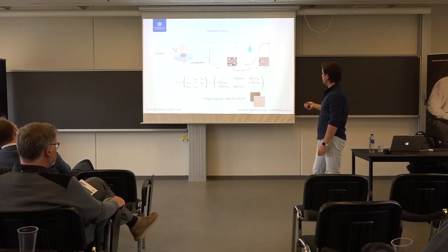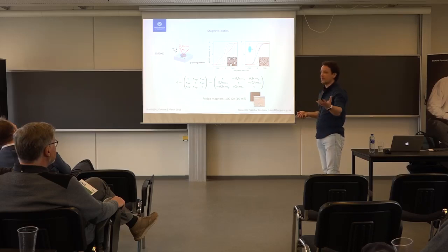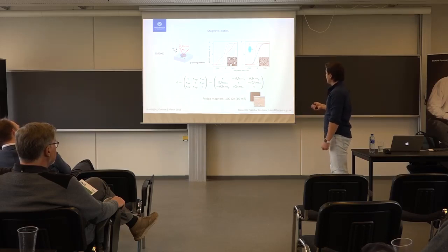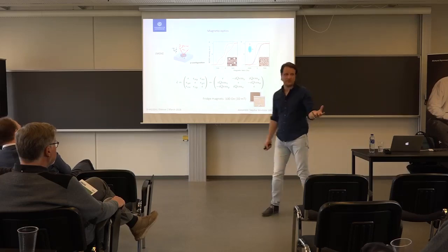Or here you would see the effect of applying the magnetic field along different axes. I mentioned the easy axis, where the material likes to be magnetized. It turns out that if you have an anisotropic structure like the ellipse, and you apply the magnetic field along the long axis, it keeps the magnetization even if you completely remove the field. This is how magnetic memory works.